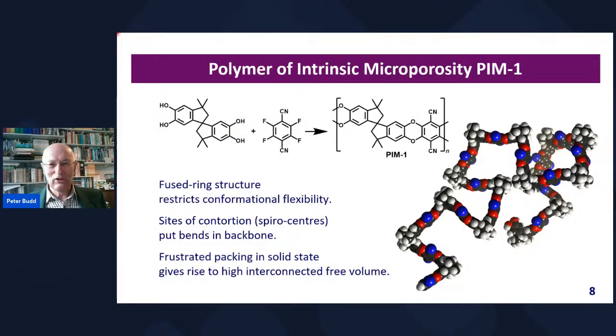with this structure is all fused rings. There's no single bonds in the backbone, so there's much less conformational flexibility than in a conventional polymer. But by having a spirocenter in the polymer, if we just look at it, here's a little bit of the structure of the polymer. The spirocenter is where we have two 5-membered rings, in this case, connected by a single carbon atom, a tetrahedral carbon atom, and so that puts a bend in the chain.